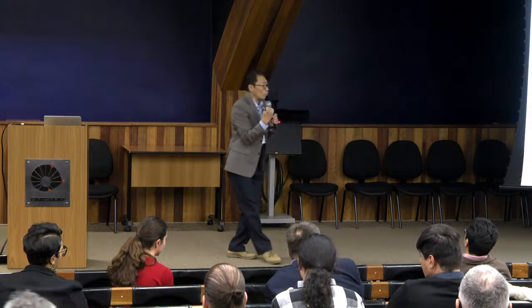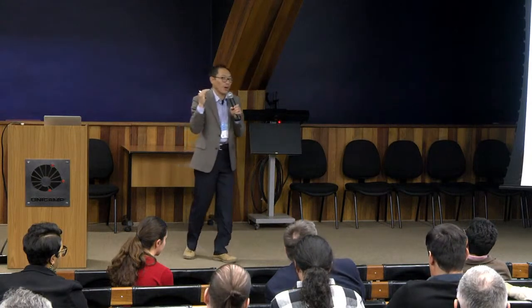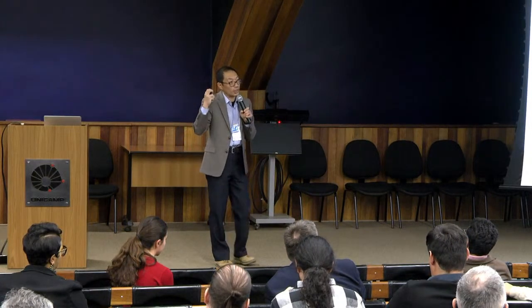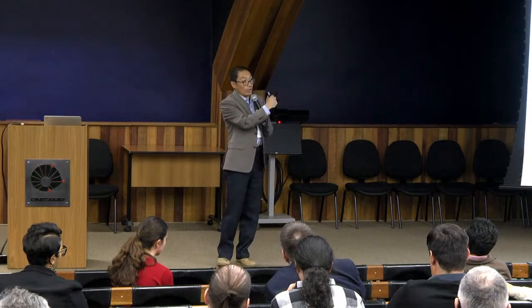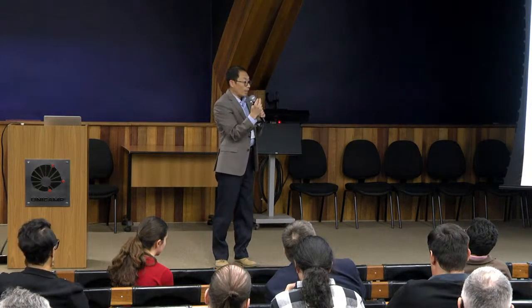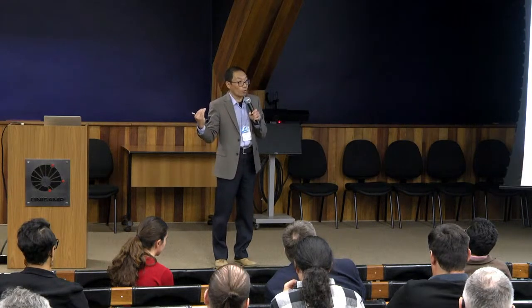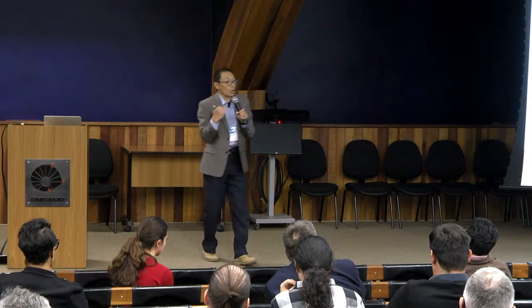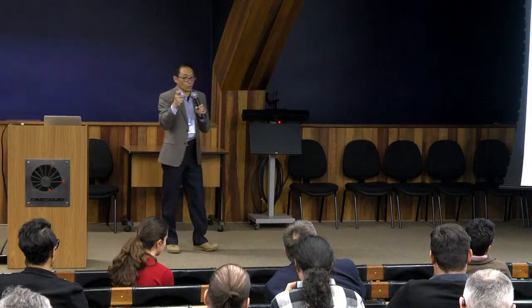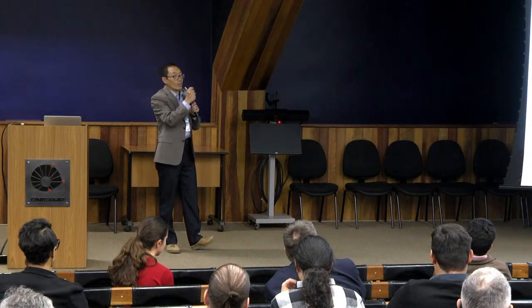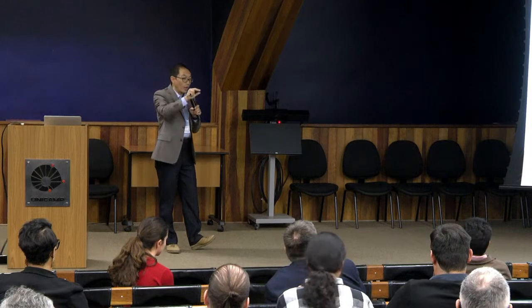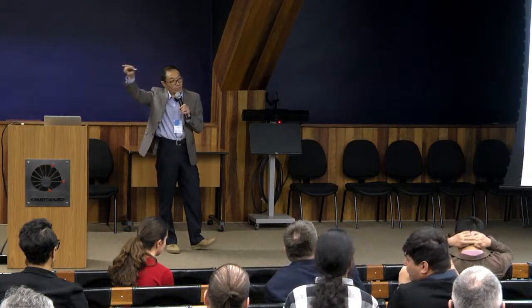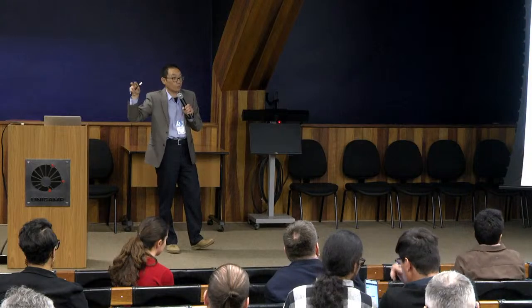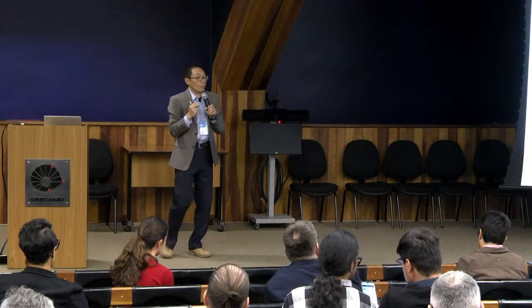We also have other works, and I really don't have time to touch all those topics, showing that by just changing the electrolyte, the oxygen redox behavior can be different, like to have it or not to have it at all. So there is really a correlation. It all goes to what kind of redox activities, whether they rely on the gradient of chemical migration to the surface, or they don't. Different redox could have different effects, but there are cases with very strong effect.